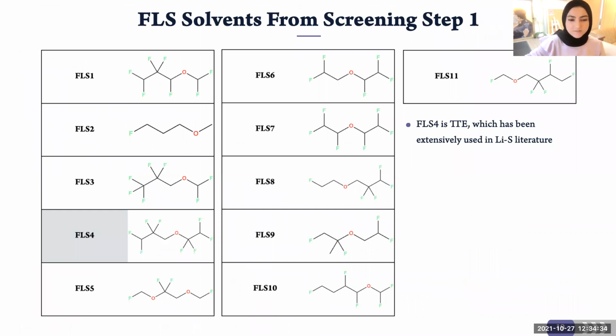The 2D structure of the selected solvents from the screening process is shown here. FLS4 is not a screened solvent, but rather TTE, which is one of the most extensively used fluorinated solvents in lithium-sulfur literature. This solvent did not meet all of the screening criteria selected in the process, but is included to show how it performs compared to the screened solvents.